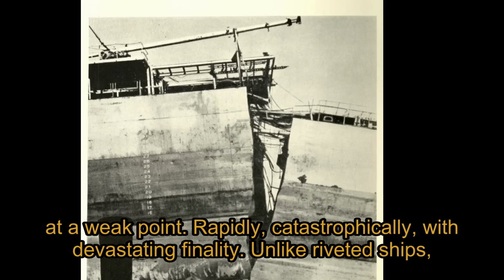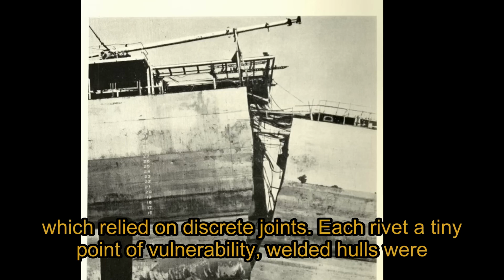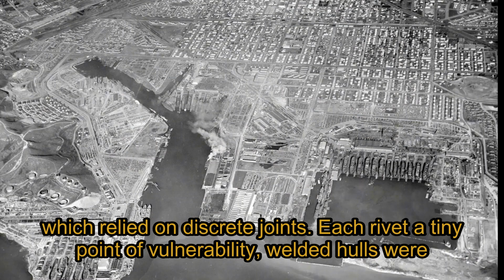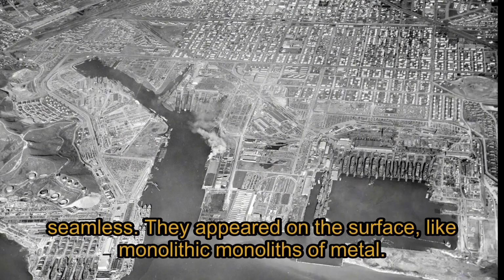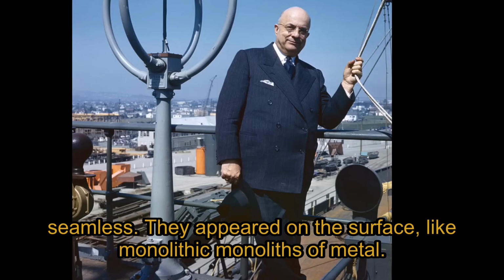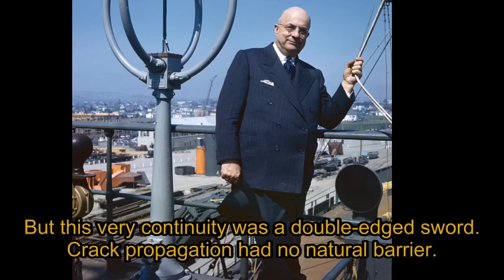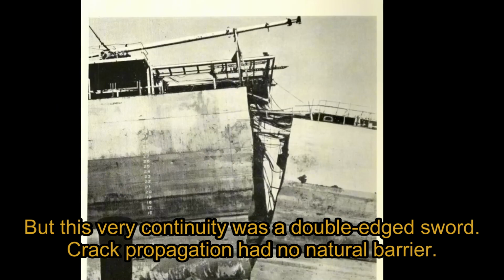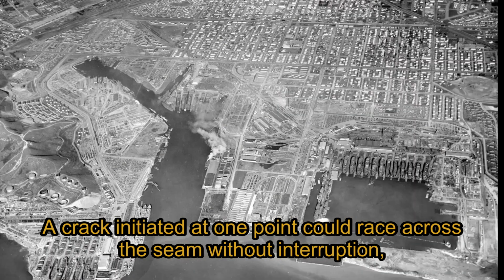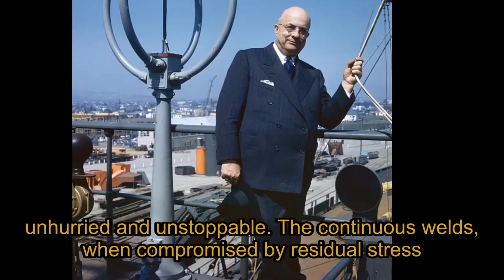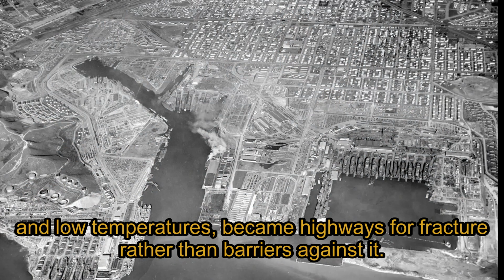Unlike riveted ships, which relied on discrete joints, each rivet a tiny point of vulnerability, welded hulls were seamless. They appeared, on the surface, like monolithic monoliths of metal. But this very continuity was a double-edged sword. Crack propagation had no natural barrier. A crack initiated at one point could race across the seam without interruption, unhurried and unstoppable. The continuous welds, when compromised by residual stress and low temperatures, became highways for fracture rather than barriers against it.